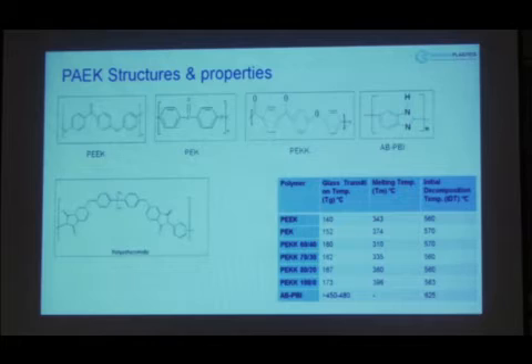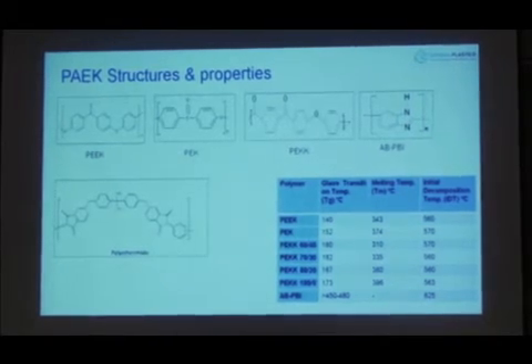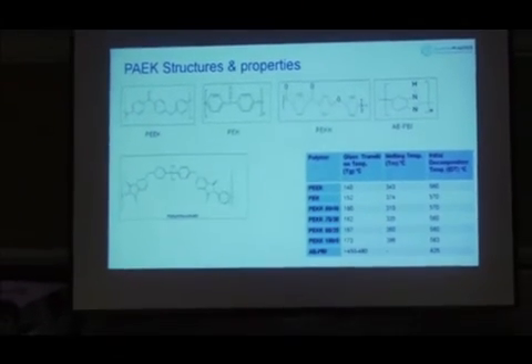You can see this unique chart. This is actual values, where you can see the polymer on the first column. So you can see PEEK, PEK, PEKK. So there are 4 different types of PEKK, which is an amazing material for 3D printing. And you can see their glass transition temperature. It is very important for laser sintering, and whenever you are doing filament extrusion and all this, these parameters are very much important. Then you can see their melting temperature and initial decomposition temperature. So most of these high temperature polymers have decomposition temperature more than 500 degrees C.